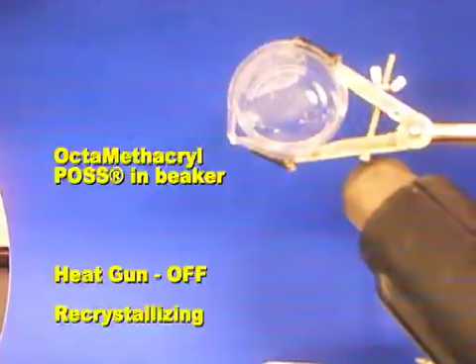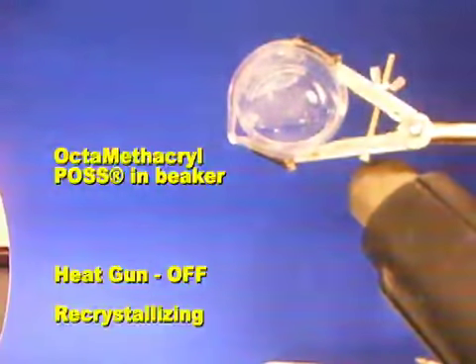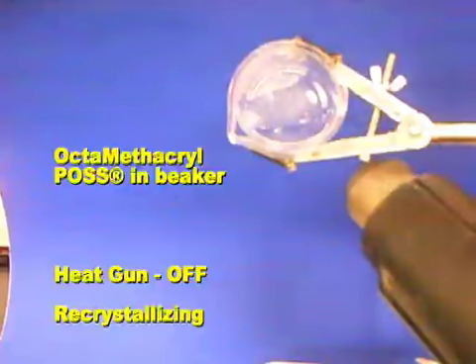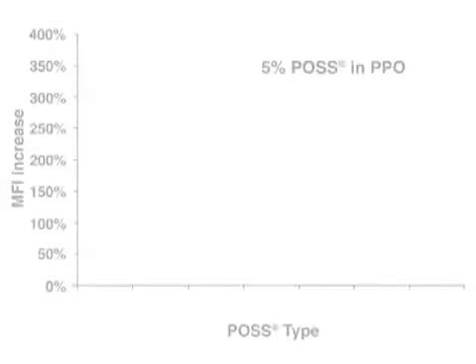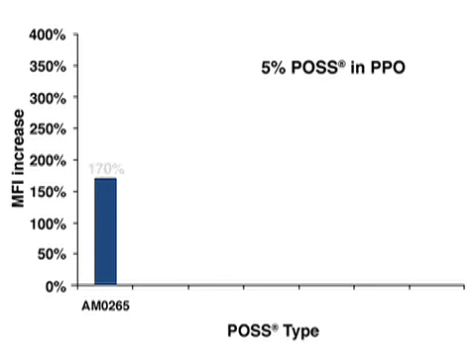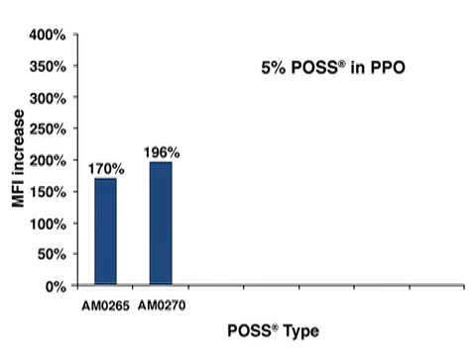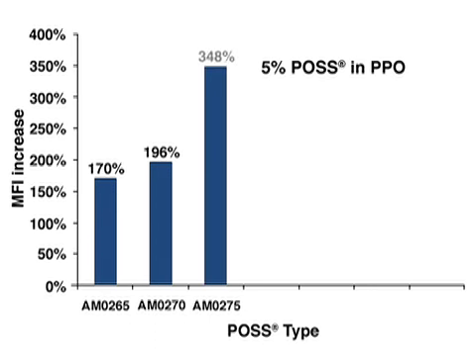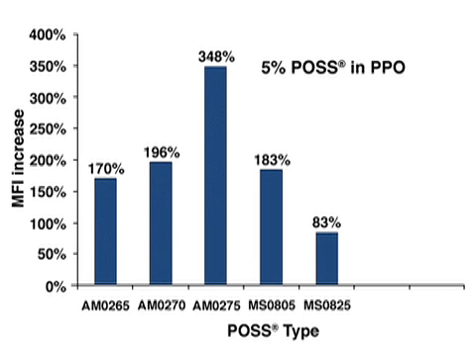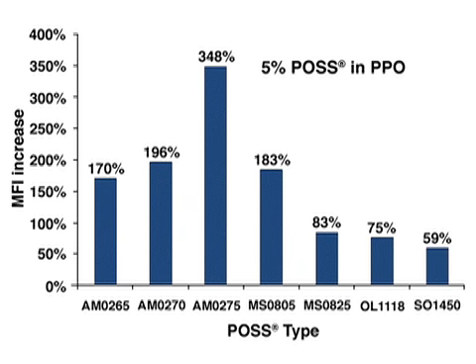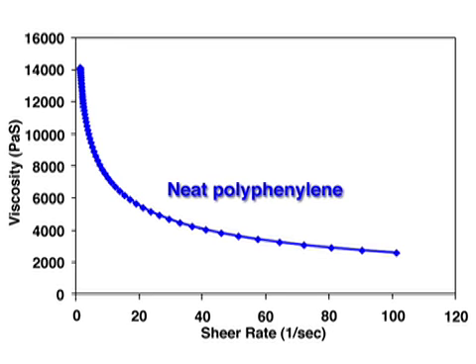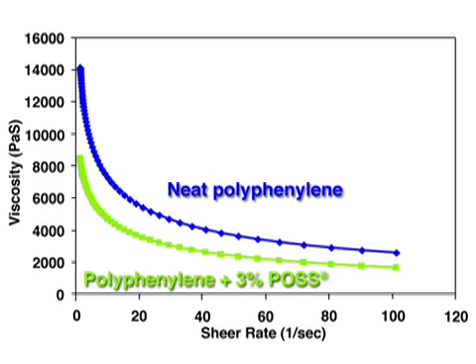High temperature stability, melting, and ease of dispersion allows POSS to be used as a flow aid for hard-to-process polymers. Polyphenylene oxide, or PPO, is very difficult to process, and therefore typically requires blending with other resins such as polystyrene. The melt flow index of PPO can be increased by up to 350% by the addition of only 5 weight% of POSS. Even polyphenylene, one of the hardest thermoplastics to process, shows a melt viscosity decrease of 40% at a range of shear rates.